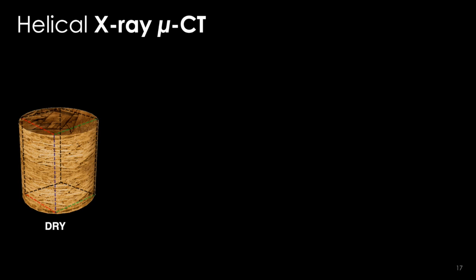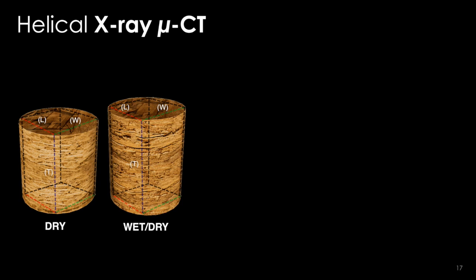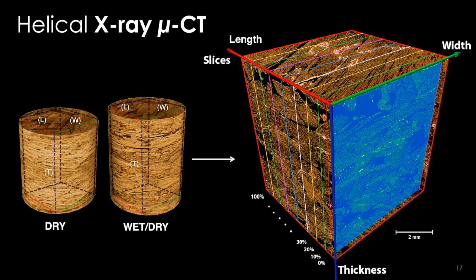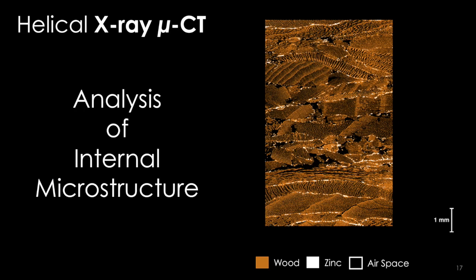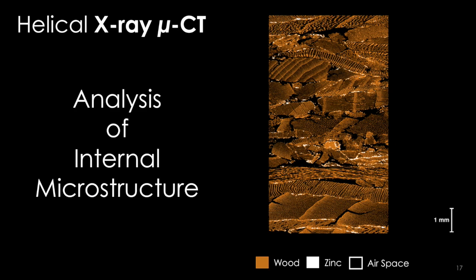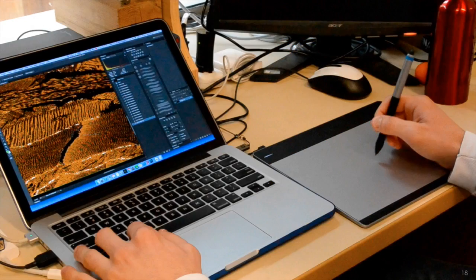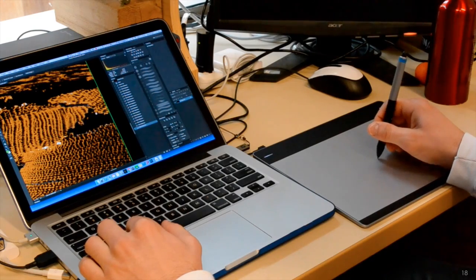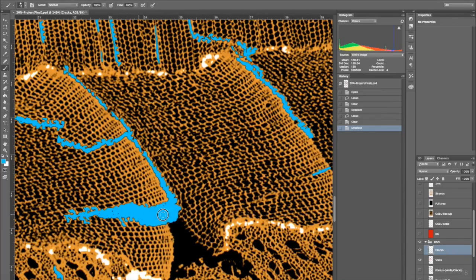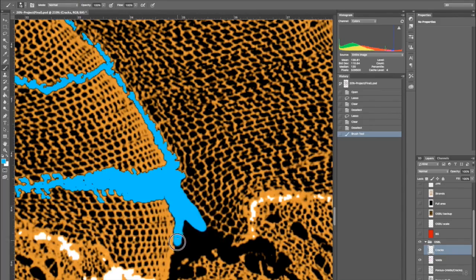So with the datasets from the sample before and after swelling, we selected the slice from 0 to 100% along the length. And then we analyzed the individual frames before and after swelling for each slice. Up to here, the phases that we can directly get using computer software are the wood, zinc, and airspace. But manual segmentation is required in order to threshold the voids and checks. We did that by using a drawing tablet with a computer.